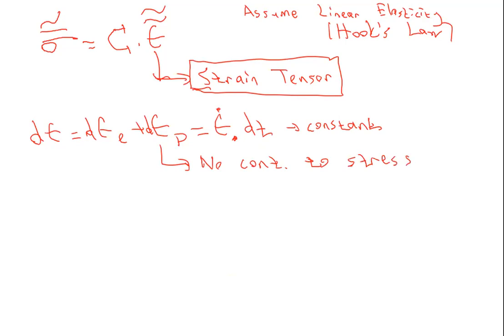In elastic regime, you only have elastic strain. Then once you multiply it with E, you can calculate sigma. But in plastic region, we have both elastic and plastic strain. Due to the contribution of plastic strain, the elastic strain decreases, and we see some decrease in the stress-strain response. So basically, the stress tensor is just modulus tensor times the elastic strain tensor. This is very important. We need to find the elastic strain tensor.